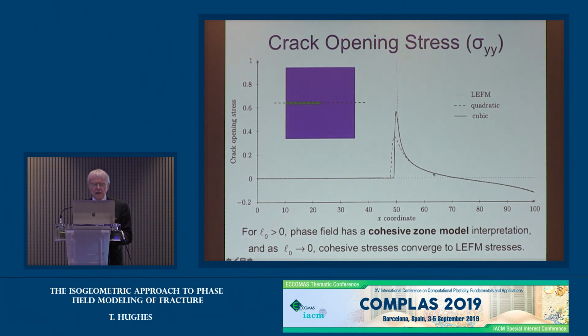Now, these different theories have interpretations as cohesive zone models. And you can see that by comparing for this problem of a crack in a plate. And you can see the stress distribution sort of, let's say, upstream of the crack, they exhibit different cohesive zone type interpretation. So all these theories, the particular function G that you use, are somewhat like cohesive zone models in that respect. And actually, it has been proposed to develop the stress degradation function in such a way that it can replicate various cohesive zone models if one is interested in that.